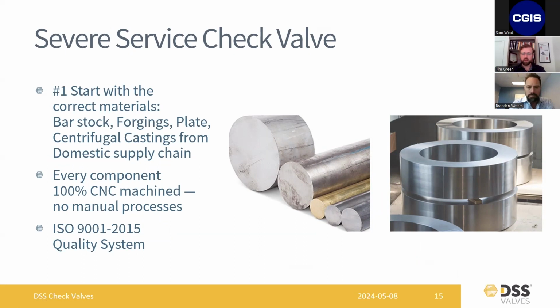Especially with a lot of the hydrogen that we're seeing right now. It's smaller bore stuff, usually 8-inch and below. We prefer to make these valves out of wrought material, meaning bar stock, forgings, plate. We can use centrifugal castings, but we prefer wrought materials because it allows us to keep very close watch on the chemistry requirement. We get these from domestic sources.